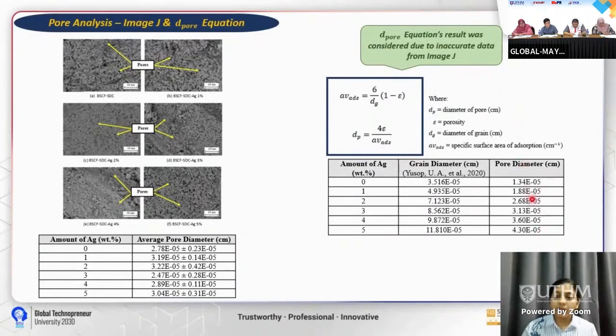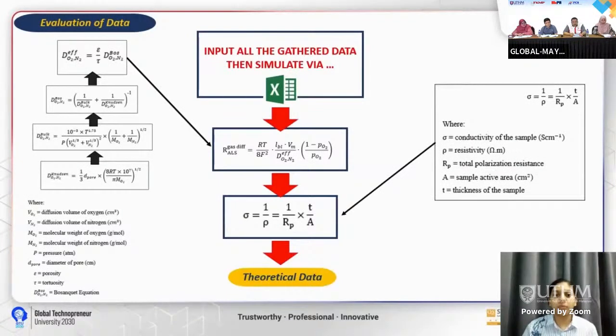So looking at both results, we are considering the D-pore equation result due to the inaccurate data from ImageJ, because the image itself is very unclear, and it's difficult to come up with nearly precise data of pore diameter. Next, all the data from experimental and additional will be gathered and then simulated through Microsoft Excel. In Microsoft Excel, we have two main formulas, the polarization resistance and ionic conductivity, which will eventually lead to the last part of the research with the theoretical data.